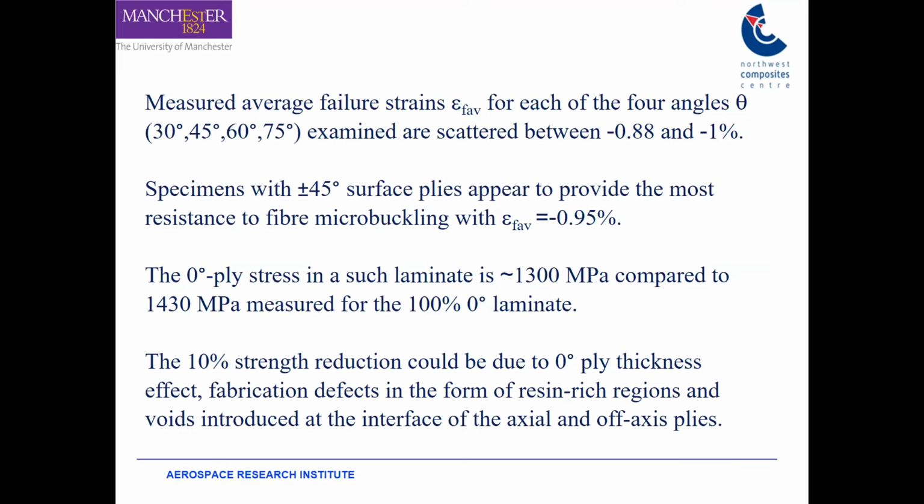The zero ply stress in such a laminate is 1300 megapascals, about 10% less than measured for the 100% zero laminate. But that can be due to blocked plies in the middle of the laminate. We have all those zeros blocked together, with fabrication defects from resin-rich regions, voids at the interface of the axial and off-axis plies.